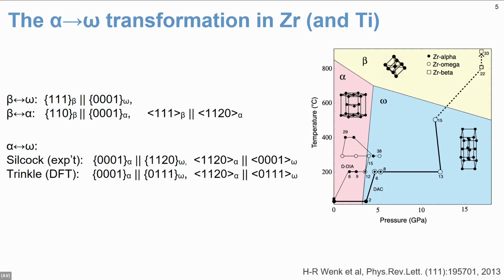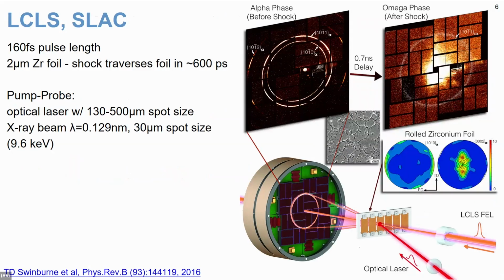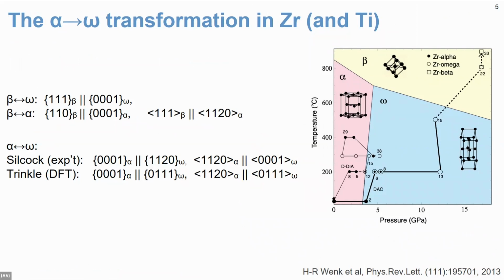So here's an example from our first experiment at LCLS. This is zirconium. It's a low temperature, low pressure HCP arrangement. At high temperatures, you have a BCC arrangement. But if you go to high pressures, then you can transform to this omega phase here, which is generally a nuisance phase. It embrittles titanium and zirconium alloys. But this sort of high pressure phase can be useful in some engineering objects in order to give you a compression boost and things like that.